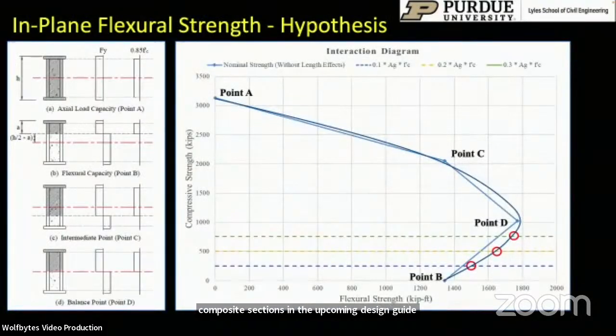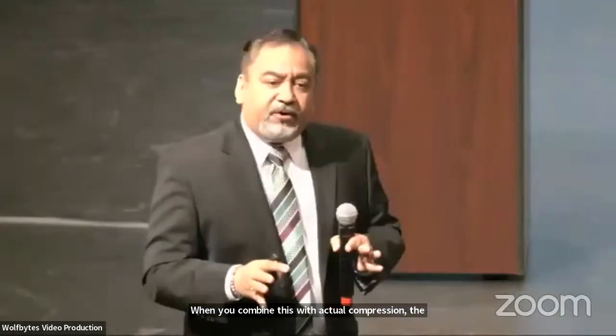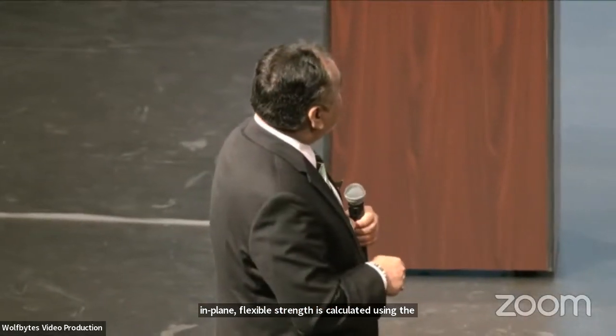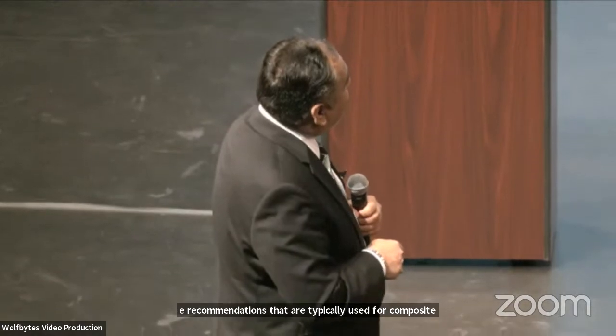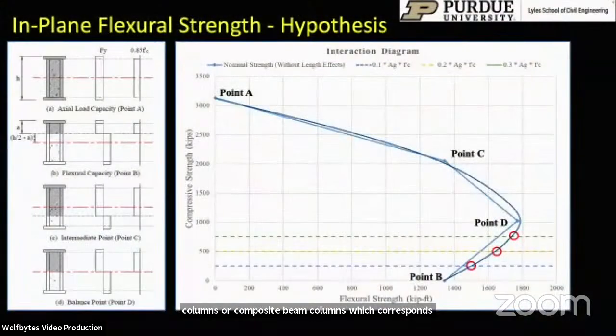When you combine this with axial compression, the in-plane flexural strength is calculated using the recommendations that are typically used for composite columns or composite beam columns, which corresponds to the axial compression point A, the flexural capacity point B, the balance point D, and of course point C, which has the same moment capacity as point B.